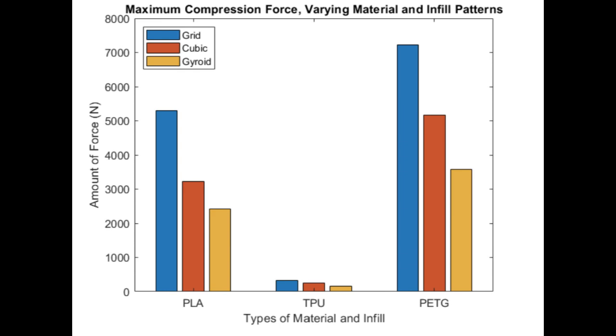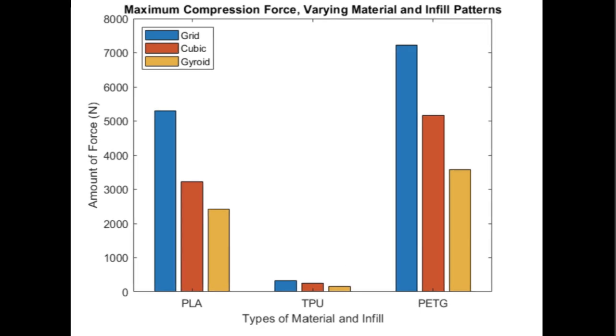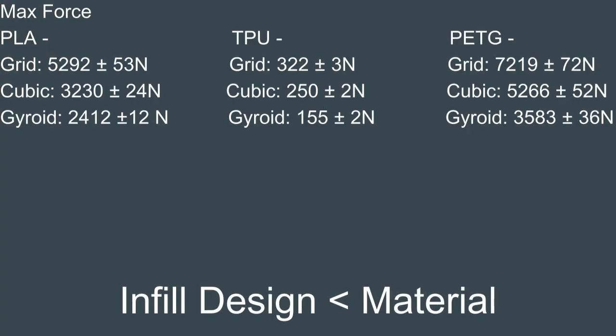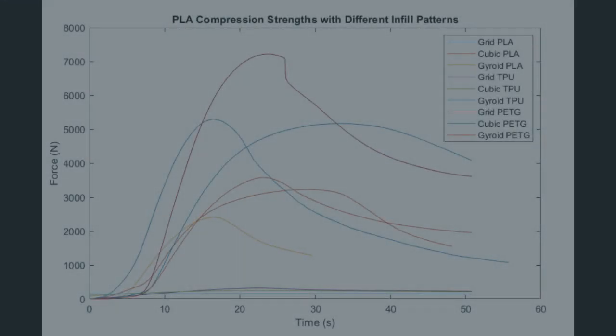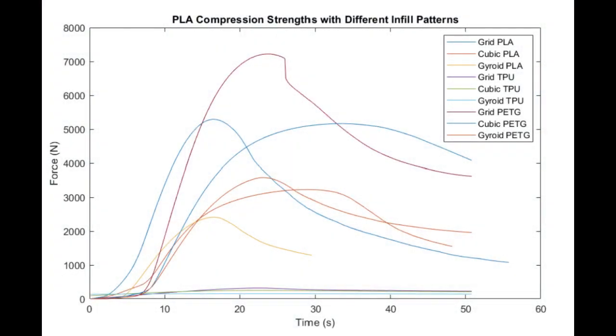On average, the results for the PET-G were about 2,000 newtons higher than the results for the PLA. The TPU results were a full order of magnitude lower than the other materials and did not even exceed 500 newtons. The material type does have a bigger influence on the results than the infill pattern, which aligns with the reasoning for our hypothesis. One interesting trend that we noticed was how the force affected each infill pattern.